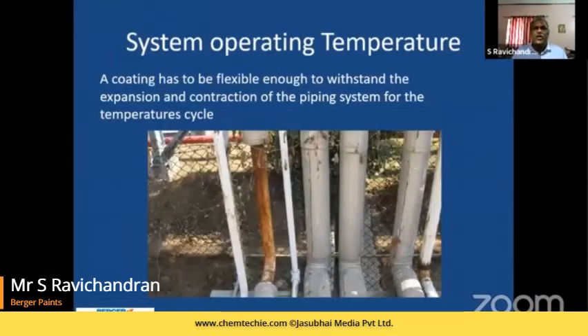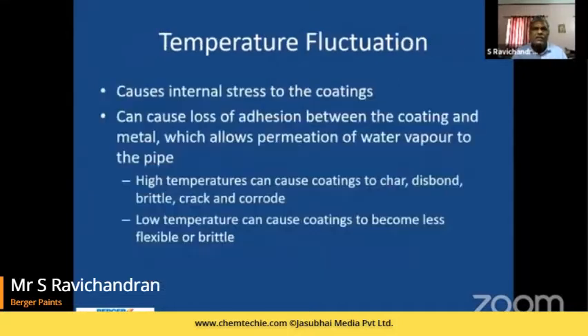materials. So when you're talking about operating temperature, the coating has to take the stress for being flexible enough to take care of the different range of temperatures and the temperature cycles. It has to take care of the internal stress, and there should not be any loss of adhesion between the coating and the material, despite the temperature increase or decrease.